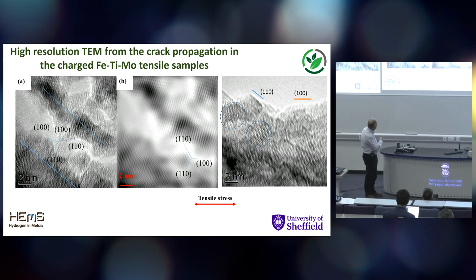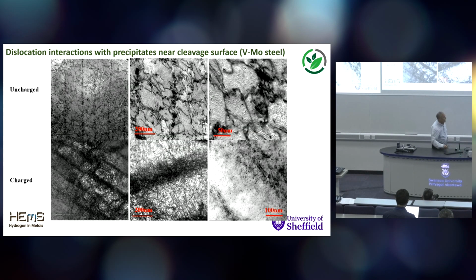And this is a crack tip here. Again, you can see the atomic planes right up to the atomically sharp crack tip there. As I said, the dislocation density is much higher at the start, and as you go near the crack, the charged specimen retains this very much higher dislocation density than in the uncharged state.